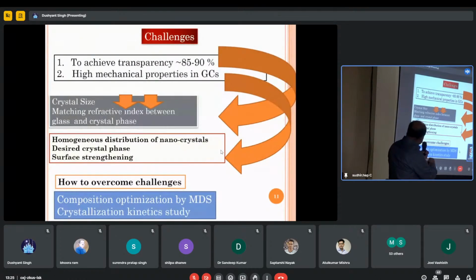In order to achieve transparency, you need to control the size of crystals, and also the refractive index must be matched between the glass phase and your crystal phase. If you can match it, then you can have very good transparency. For mechanical properties, you need a homogeneous distribution of nanocrystals, the desired crystal phase, and surface strengthening. Ion exchange you can also do with this kind of glass. Molecular dynamics simulation and crystallization kinetic study actually help in controlling crystallization.